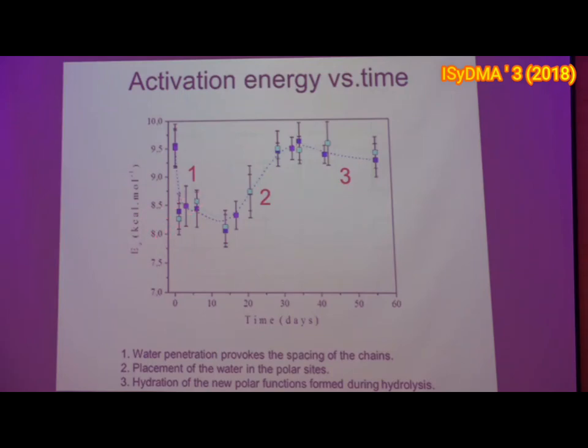So this is what happened over time. Okay, we see the activation energy decreases in the first moment. This is due to the water, because we put these films in constant humidity, so the water goes into the film. This penetration provokes the spacing of the chains, and this activation energy in the first times decreases. Then in the second moment it increases, okay. This is the placement of the water in polar sites.